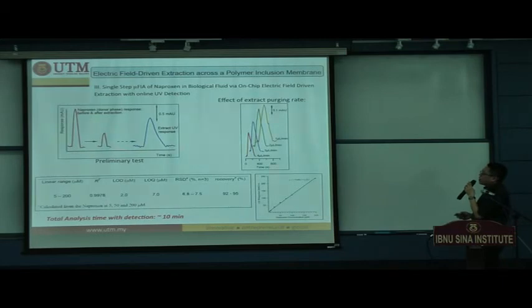One of the major parameters is the purging flow rate that we should use. If you use too low a purging flow rate, there is dispersion of your enriched analytes along the tubes, which causes a very broad UV signal. And if you use too high a purging rate, it actually results in very sharp peaks, but the peak area and the sensitivity will be much lower.